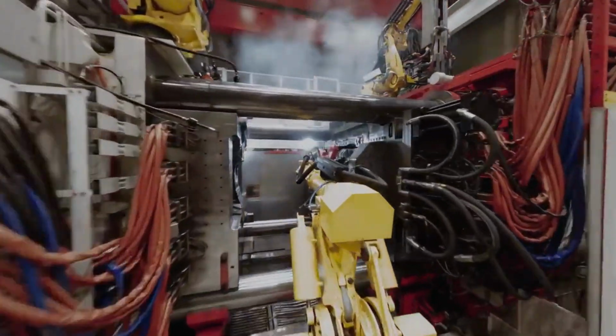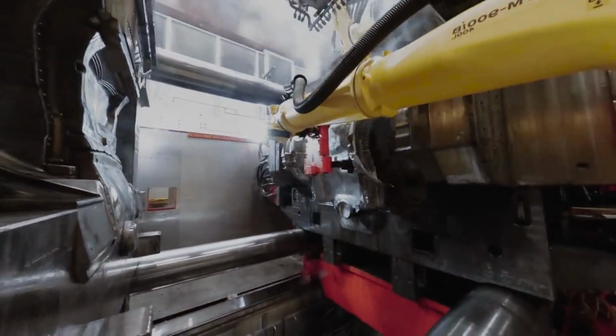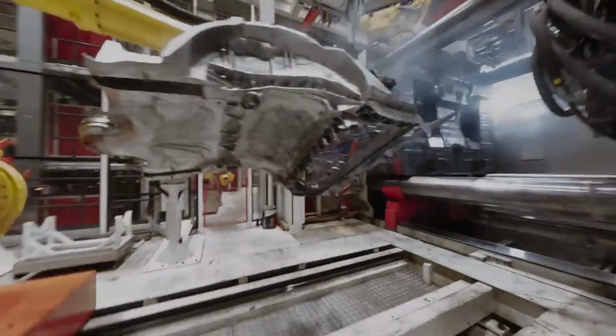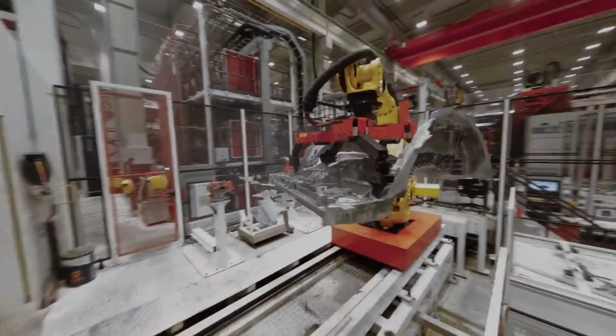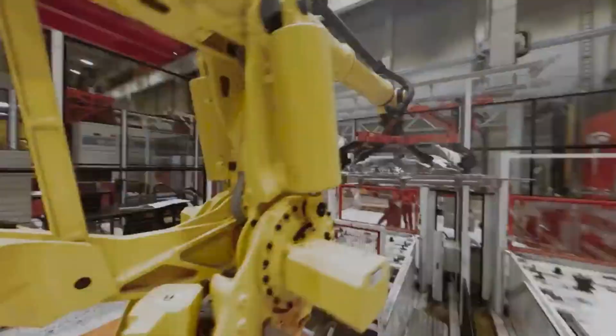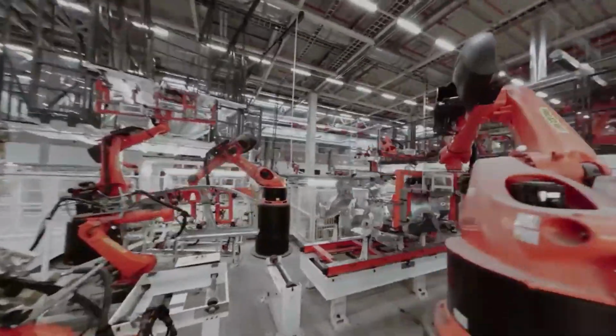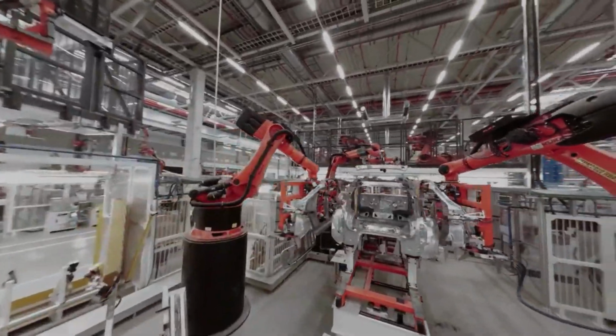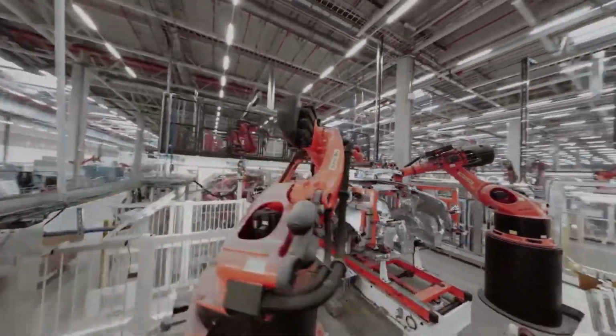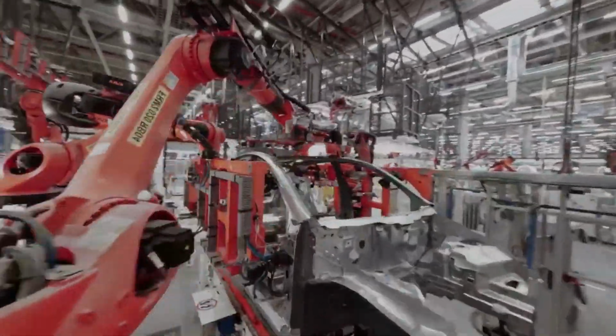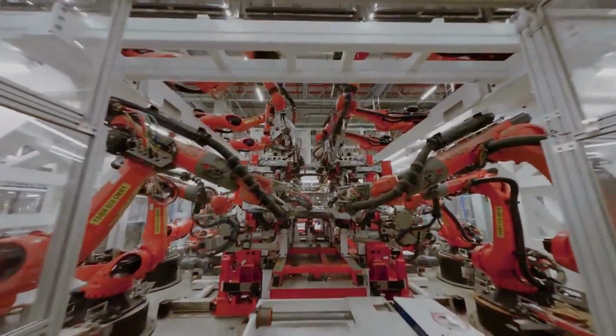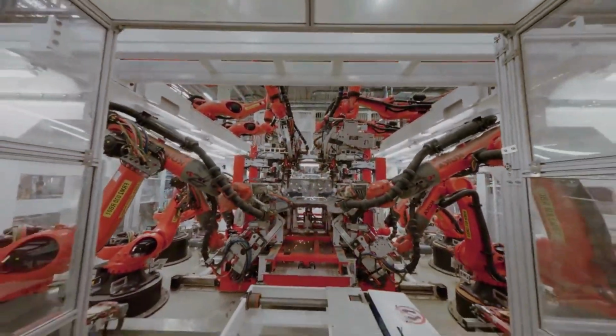Casting. From the holding oven, the molten aluminum is sent to the shot chamber of the GigaPress. There, a high-speed plunger is used to drive the molten metal into the cavity. Additionally, 8 milliliters of oil are used to lubricate the plunger before each shot. The casting is injected and then left inside until it solidifies. At 400 degrees C, the casting is then released from the dies.